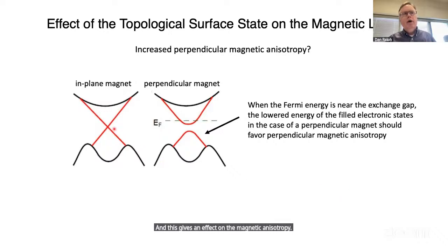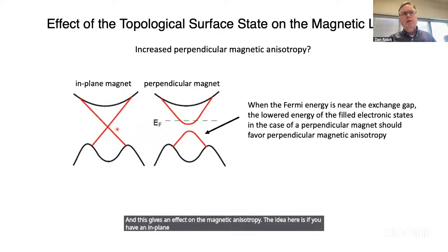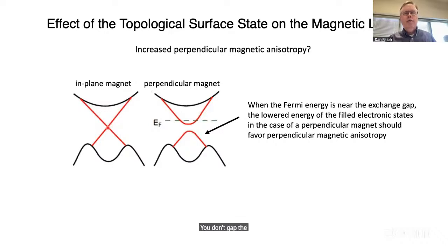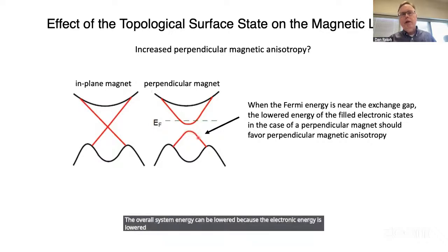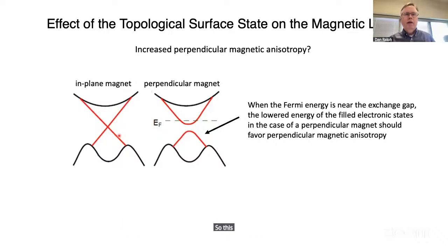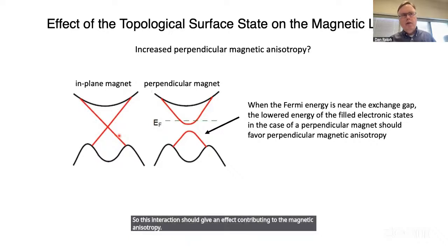The idea here is if you have an in-plane magnet interact with the topological surface state, you don't gap the surface state, so you still have the Dirac dispersion. Whereas with the perpendicular magnet, as I mentioned, you expect to gap the surface state. What this means is if you have a Fermi level near the gap, the overall system energy can be lowered because the electronic energy is lowered if you have a perpendicular magnet compared to an in-plane magnet. So this interaction should give an effect contributing to the magnetic anisotropy, favoring an out-of-plane orientation rather than in-plane orientation.